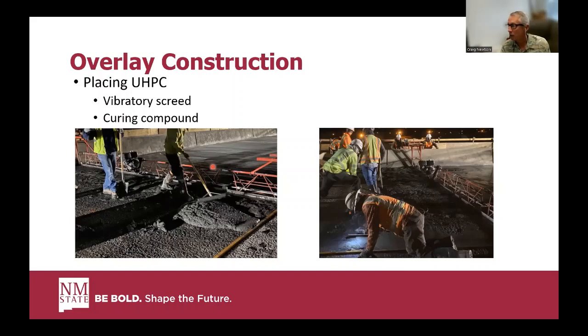When things went well, there was curing compound getting placed, getting sprayed right behind the screed to control moisture loss. And then right behind the curing compound application, we wanted to get plastic down. When that happened, things went well. At the very beginning of the placement, that wasn't happening. So we placed the overlay in 4 placements. The first placement, probably the first half of it, the plastic wasn't getting down fast enough behind the curing compound, and there was cracking in that region, and I would call that cracking moderate. But I'll show you a picture of it shortly.